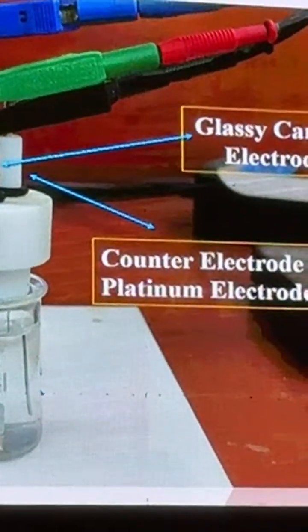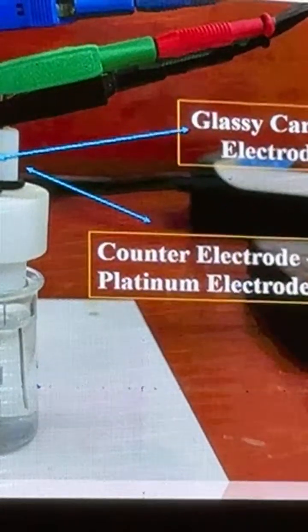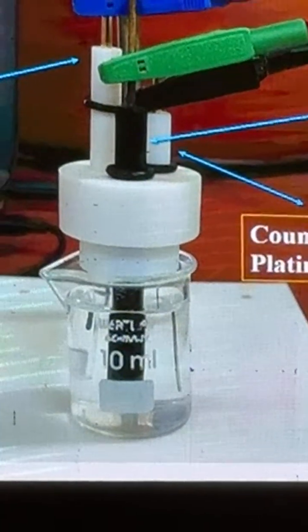So BGCN material was dispersed in distilled water through sonication, and Nafion was added, which is the conducting binder, and the suspension was dropped on the surface of glassy carbon, and after drying it was used for sensing. So this is a 3-electrode system in which the reference electrode is silver chloride, the glassy carbon is used as the working electrode, and for the counter electrode we use a platinum electrode. Real samples were collected across the district of Jamshoro, Indus River and Kotri, and they were stored in the refrigerator. Then the samples were filtered, cleaned and pre-concentrated through solid phase extraction, and then eluted with acetonitrile.